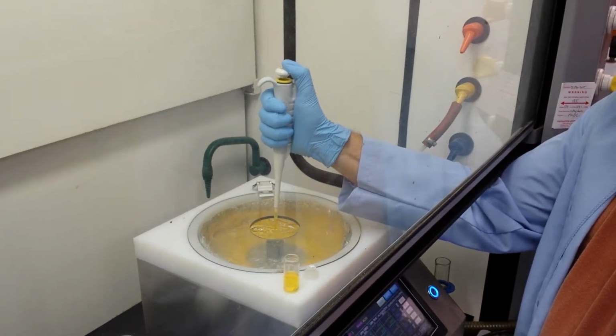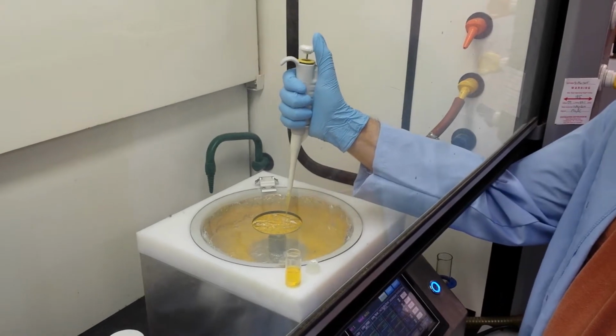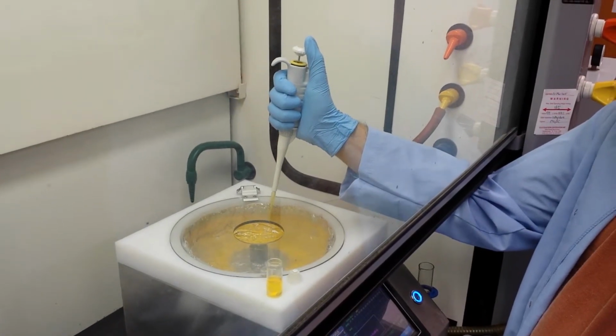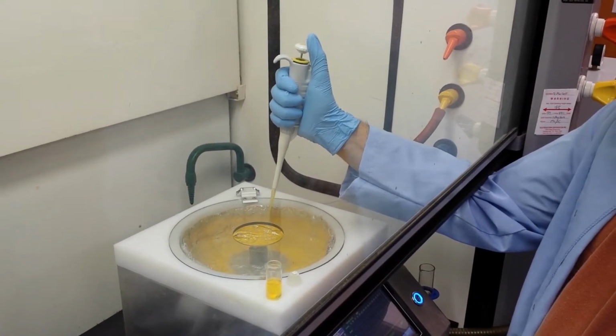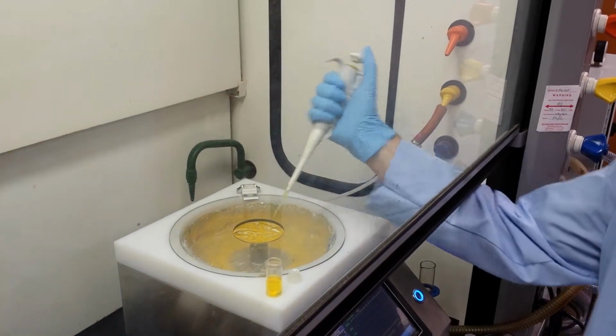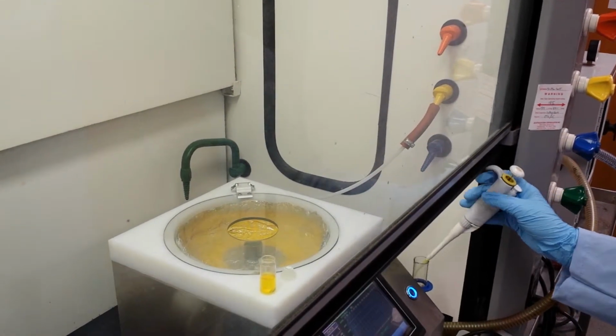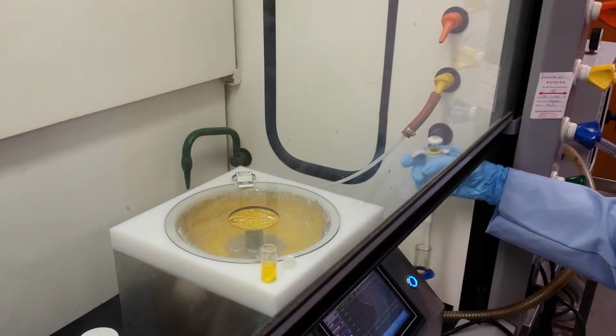So what we do is we deposit the solution onto the substrate, and then we run it. And what this will do, like I said, is it's going to wait for 7 seconds and then spin for 20 seconds.